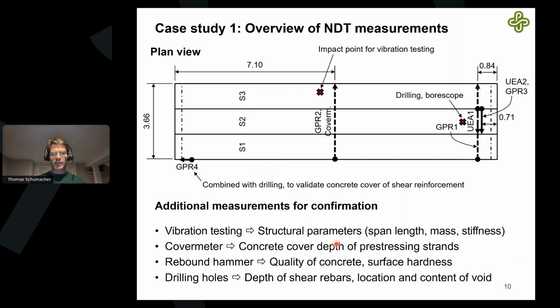The cover meter I mentioned gives us a reliable depth of the pre-stressing strands. We also used a rebound hammer, a Schmidt hammer, to give us an idea of the quality of the concrete, the surface hardness. And then we drilled some holes. In one hole here, to confirm the actual cover of the shear bar, and another hole, as I said, to drill into the void.